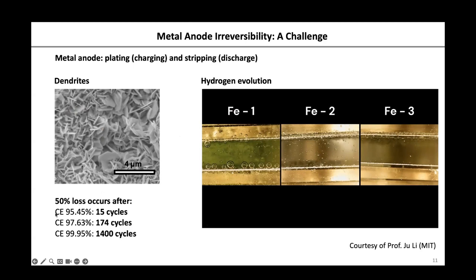If you have a Coulomb efficiency of 95%, that sounds pretty good, right? You're going to lose 50% of your electrode in just 15 cycles. So if you use twice the capacity of your anode compared to the cathode, 15 cycles later, the excess capacity from your anode will be gone. That is 174 cycles for 97.63%. And if you have a very nice Coulomb efficiency, 99.95%, that battery can last 1400 cycles with 50% of the mass lost on the anode side.